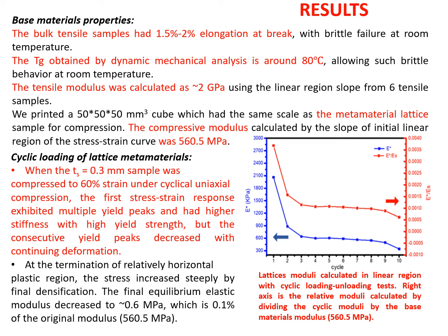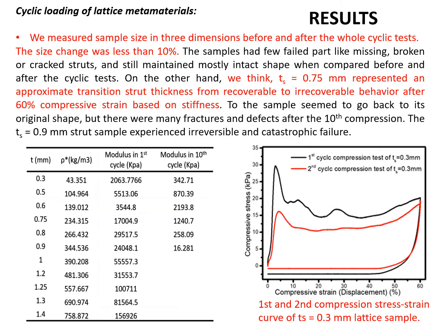At the termination of the relatively horizontal plastic region, the stress increased steeply by final densification. The final equilibrium elastic modulus decreased to 0.6 megapascal, which is 0.1% of the original modulus of 560.5. This situation is shown in the graph with the arrow. You can see that by the time we reach 3 cycles, this condition is reached. So we have an initial abrupt monotonic decrease in the elastic modulus. It then levels off, reaches a plateau, and decreases mildly as we increase the cycles to 10.